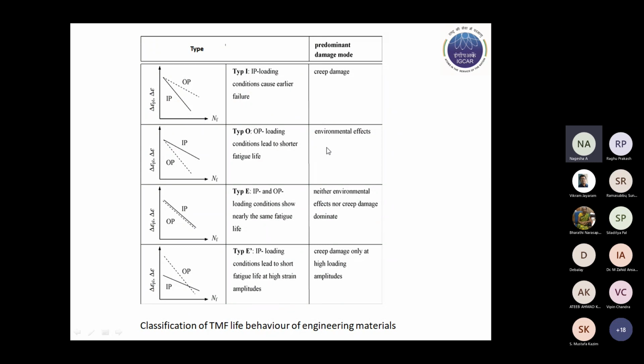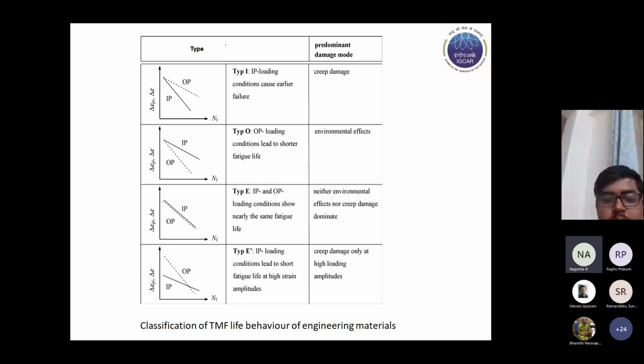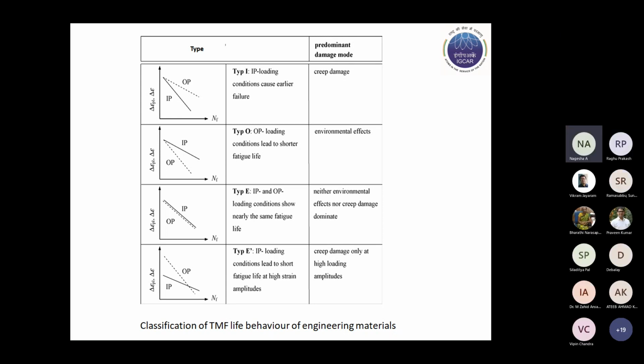Whereas when environmental effects predominate, the situation becomes reverse. So OP TMF tends to give rise to lower life compared to IP. And there are two other types wherein IP and OP almost give rise to similar lifetimes, wherein neither environmental factors nor creep damage dominate. And another type of variation is called E prime, where IP loading conditions give rise to shorter life compared to OP, and the creep damage occurs only at the high loading amplitudes.